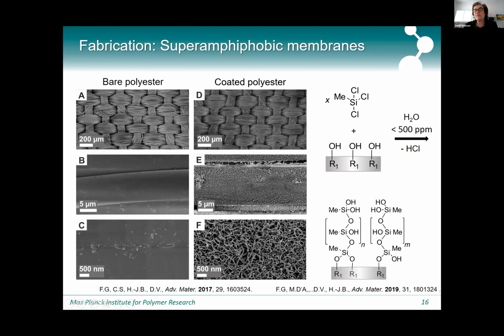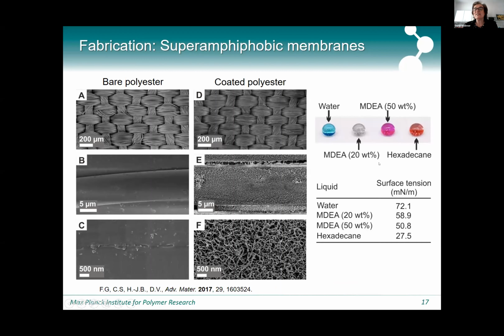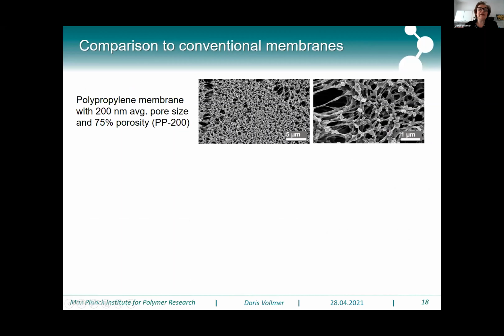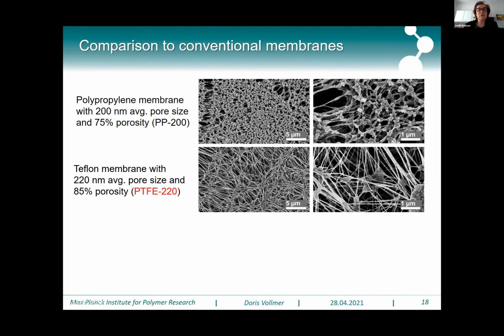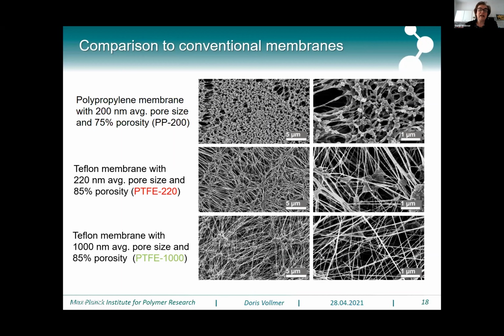Without further treatments, the surfaces are hydrophobic but not superamphiphobic, because we have methyl groups, and therefore we exchange the methyl groups for fluorine groups. And thereafter, as you see here, the amine droplets as well as hexadecane droplets nicely rest on this surface, forming nice spheres, and they roll off as soon as the surface is tilted a little bit. For comparison, we investigated polypropylene membranes. Here, commercial ones with 200 nanometer average pore size and 75% porosity. Teflon membranes with 220 nanometer average pore size and 85% porosity. And Teflon membranes having even larger pore sizes.